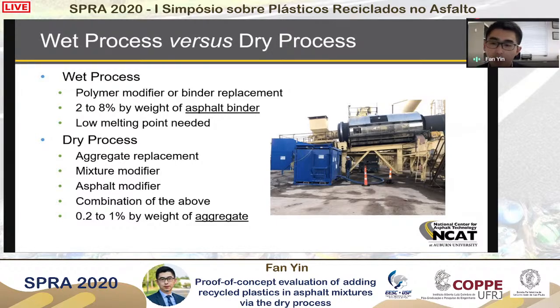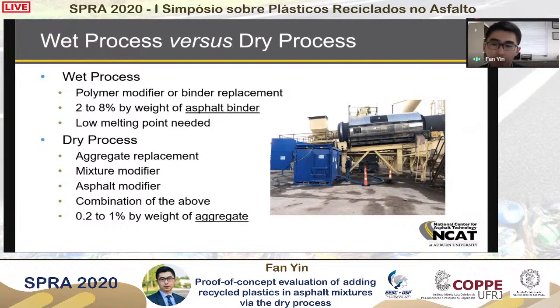On the other side, we have the dry process. It's a little bit different process where we're adding the recycled plastic into the mix. Right now, I don't think there's a good understanding about what kind of role recycled plastic plays in the mix. Do they play as aggregate replacement, mixture modifier, asphalt modifier, or a combination of all the above? Based on the existing literature that we found, the typical dosage for dry process is 0.2 to 1% by weight of aggregate. So there's a little bit of difference between the wet process and dry process. And overall, dry process can accommodate more recycled plastic for use in the asphalt mixtures.